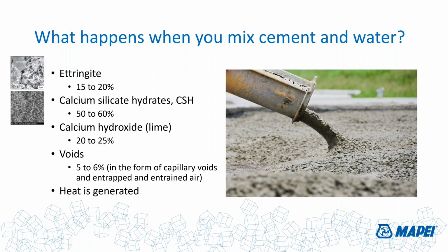So it's important to understand that the two really important aspects of this concrete's strength and its ability to be that synthetic rock are the crystalline structures formed by the ettringite, which are the long spindly crystals, and the calcium silicate hydrates, which are the ones that really build the strength. And that's the shorter crystals, but they're more integrated. We can see some pictures of what they might look like in those electron scanning microscope images